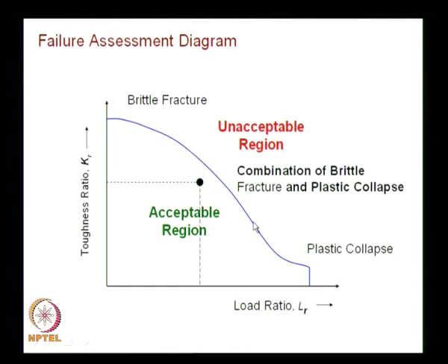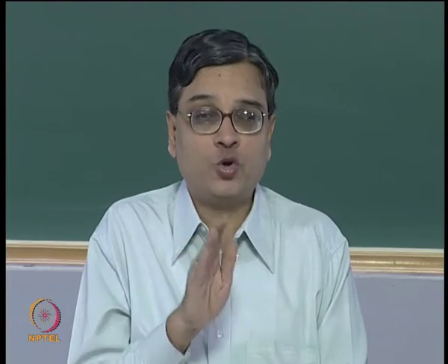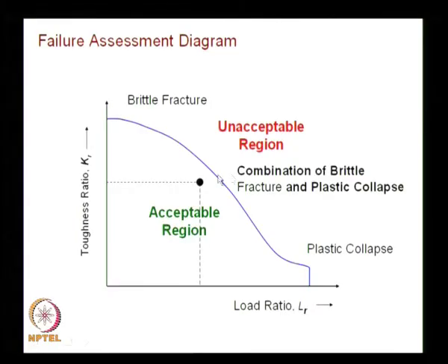So, the recommendation is do not do these analyses separately. Look at the FAD diagram. People have shown examples where it satisfies LEFM independently, it satisfies plastic collapse independently, but still the structure is not safe because the point was lying outside the FAD curve. So, such examples people have demonstrated, and you have to take knowledge from that.